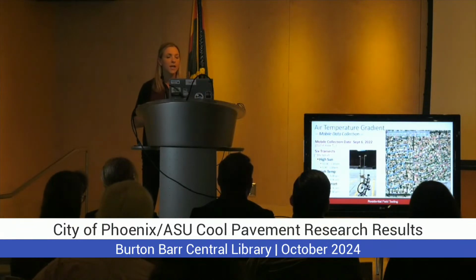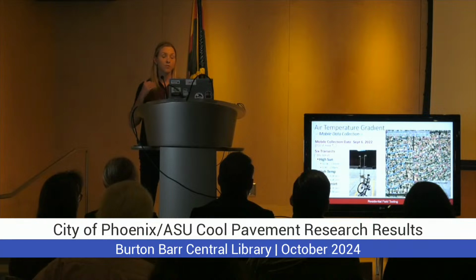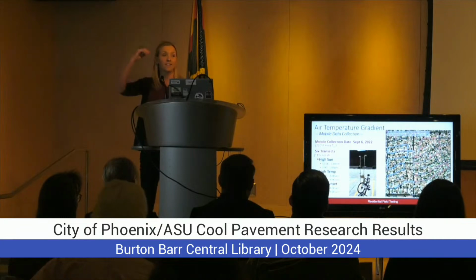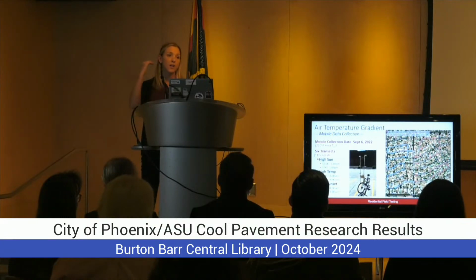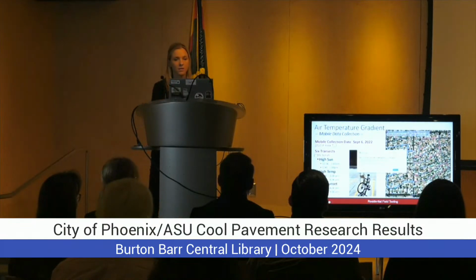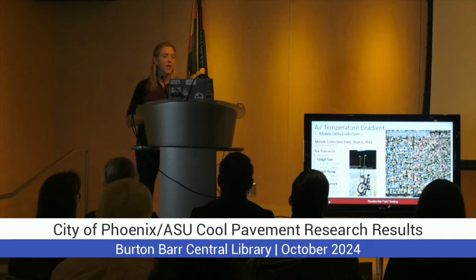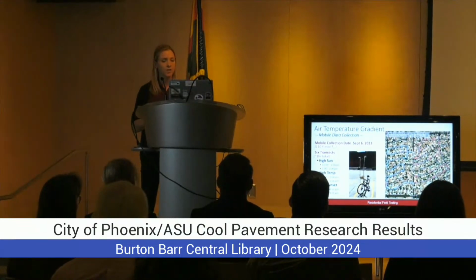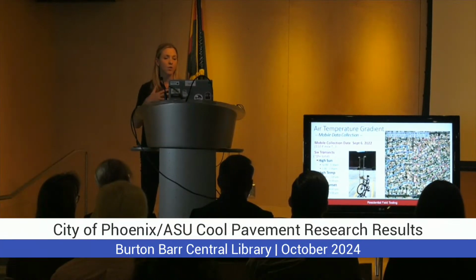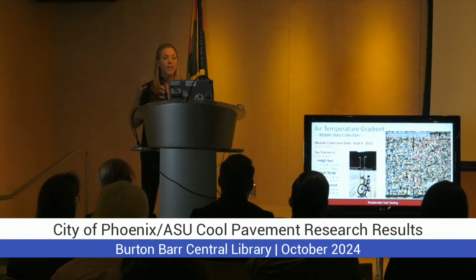With the air temperature gradient, we wanted to use some novel methods to try and see what was going on at different heights above the surface. So we did 0.5 meter, 1 meter, 1.5, and 2 meters on this mobile cart, and then also in a stationary setting. With the mobile ones, we did 6 transects on September 6th. It reached 110 degrees Fahrenheit that day, so it was a good day to do these measurements. And our student, Zach Van Tol, rode a bike with this contraption on it through these areas of the neighborhood, comparing it to also a stationary site.